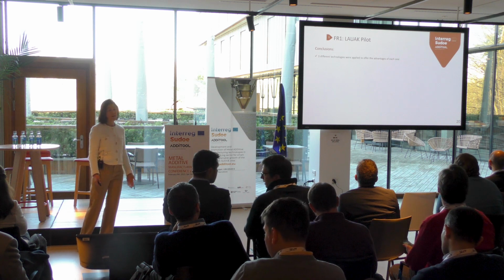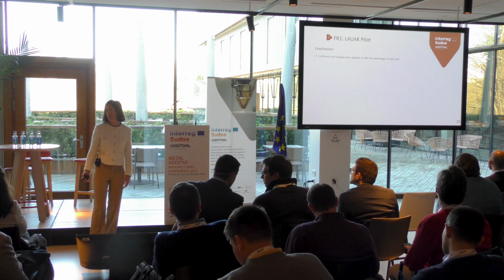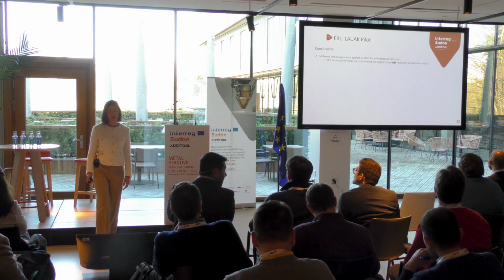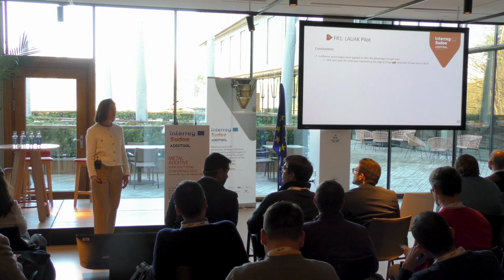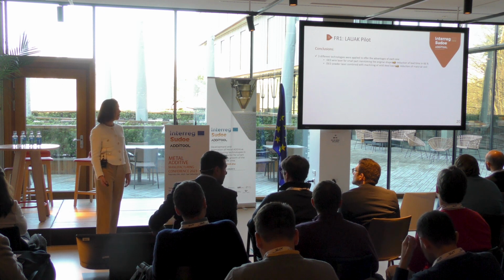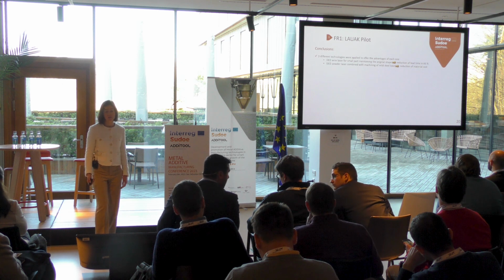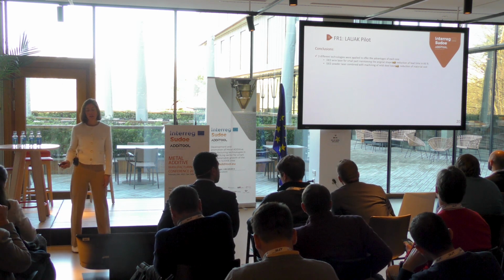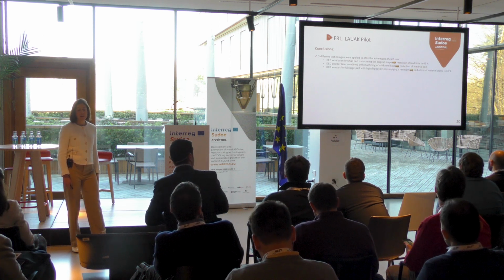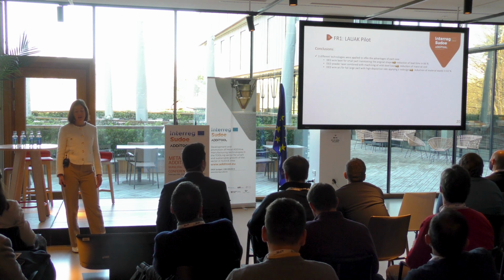As conclusions, 3 different technologies were applied to offer the best advantage for each part. The DED wire laser obtained a reduction of lead time of 66%. The DED powder laser offered a reduction of material cost using a hybrid or multi-material part. And the DED wire arc obtained a reduction in material waste of 63%.